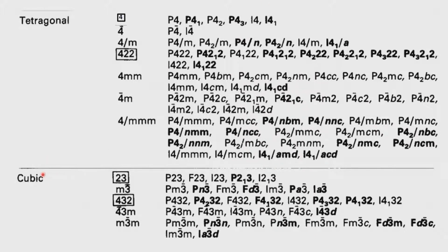On the other hand, if we go to the cubic system now, the cubic system has several point group symmetries, and cubic is unique because we have a equals b equals c, and alpha, beta, gamma are 90 degrees. The only clear cut symmetry that must be present in a cubic system is the threefold symmetry, and that should be along the diagonal. If you see the threefold symmetry here, 3, 3 bar, all these symmetries are along the 1, 1, 1 crystallographic direction.